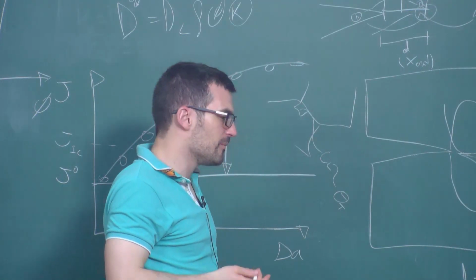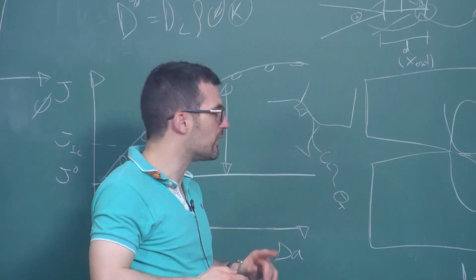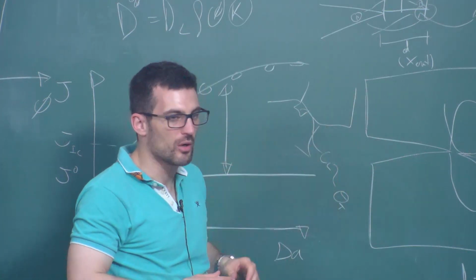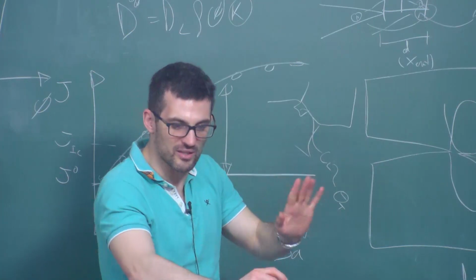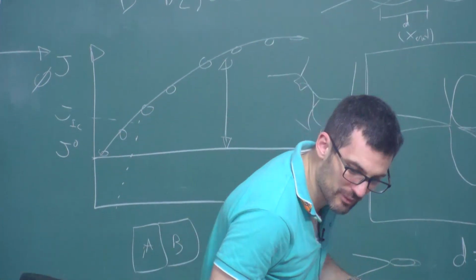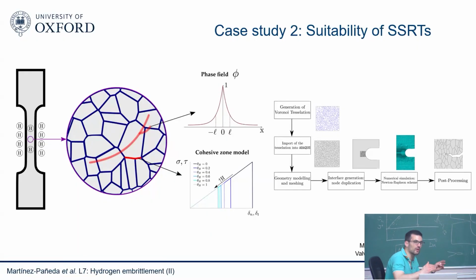We have some sort of segregation energies and so on. It was not the case of this paper. This paper was the simple approach. I can show you later. We haven't published anything about that, but I think it's a bit more rigorous. And it's a bit more complicated as well, but a bit more rigorous to capture the transport to grain boundaries and so on. We do have one paper published where we have some sort of permeation models with grain boundaries where we account for some segregation factors, so you can see the transport to grain boundary. In principle, I can always say, hey, this particular element belongs to the grain boundary or near grain boundary. This is the approach here. It will have a different binding energy, and the bulk will have, let's say, a different binding energy.